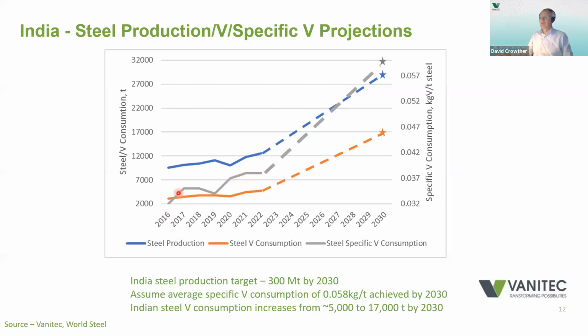The grey line is what we call the specific vanadium consumption, and this is the average amount of vanadium used in every ton of steel. So as we move to using more high strength steels, we expect to see more vanadium used. And you can see that again, this line is trending upwards, showing that more high strength steels containing vanadium are being used. At the moment, India has quite a low value for this specific vanadium consumption compared with the world average. And that means that perhaps India is using less high strength steels containing vanadium than the rest of the world. Again, that means India has great potential for vanadium containing HSLA steels.